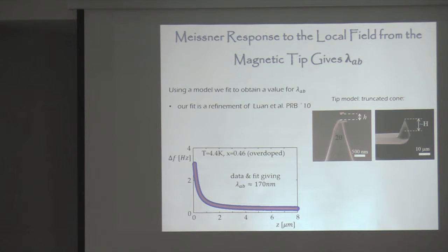Is this the best way to model it? It's basically related to the model. We're trying to get rid of the model. I don't like using a model, but we're not there yet. So there are issues with this. I have a whole sequence of slides about problems with the fit, because you can get a good fit and get the wrong result. So there are tricks that you have to do.